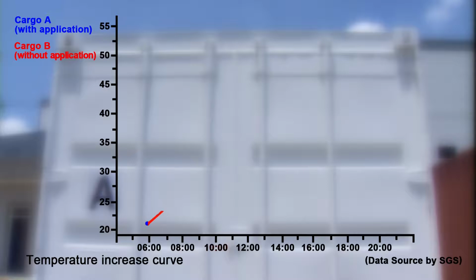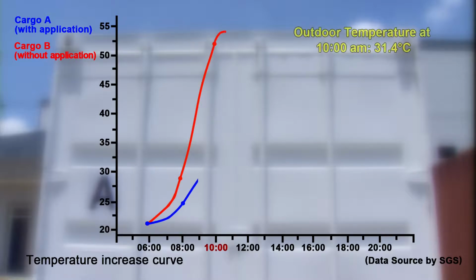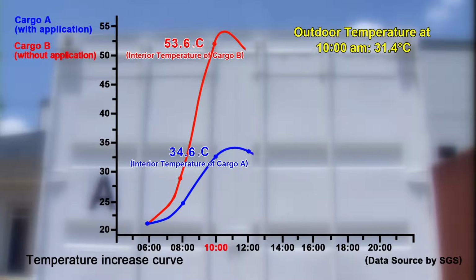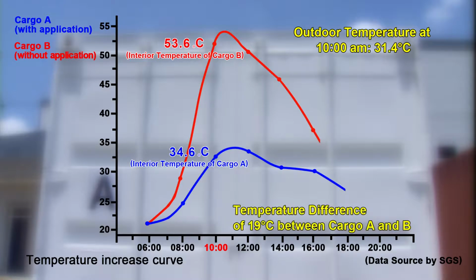According to the experiment, the two cargo containers tended to have equal temperature readings at 6 a.m. before sunrise. However, the interior temperature of Cargo B had reached 53.6 centigrade at 10 a.m., while the outdoor temperature was 31.4 degrees centigrade, whereas Cargo A in the control group revealed a temperature of 34.6 degrees centigrade, a magnificent difference of 19 degrees centigrade. At 6 p.m., the interior temperature of Cargo A had come to the same reading as the outdoor temperature, while that of Cargo B did so at 8 p.m.